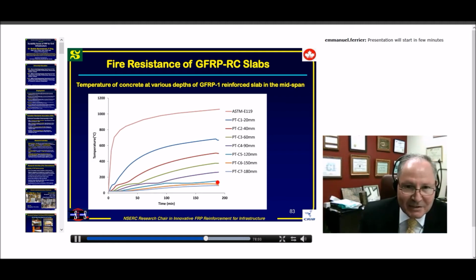the glass transition temperature. And as you are going, like here at 20 millimeter concrete cover, we have this one, which the temperature is really very high. And if I look at the concrete cover of 60, because all the bars were at a concrete cover of 60 millimeter, which is this green one. As you can see here, these bars were having 110 Celsius, like the Tg, and you can see it from here. Approximately, we reached that in less than 1 hour, as you can see here. So all this is well above the Tg.